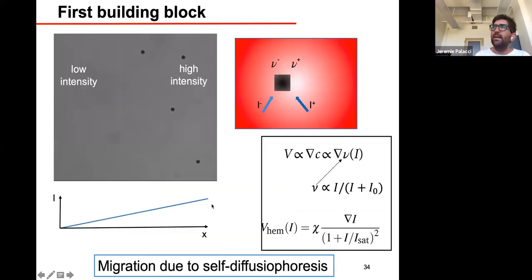So the question we asked then was, what happens if we put this particle in a gradient of light? So here we have high intensity of light, low intensity of light. The black things are hematite cubes. And what we see in this movie, which is accelerated, is that the particles move along the gradient. The reason for that is that the reaction rate is a function of the light intensity. So we have a higher reaction rate on the bright side than on the dark side. And as a consequence, the particle is going to self-generate a gradient, and it can move.